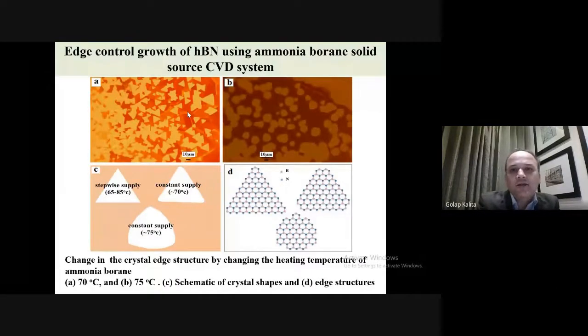Then what we can do is, the same as graphene growth, we can control the edge structure. By manipulating the growth process, we can grow perfect hexagon crystals, or truncated triangular crystals, or imperfect round or hexagonal structures.